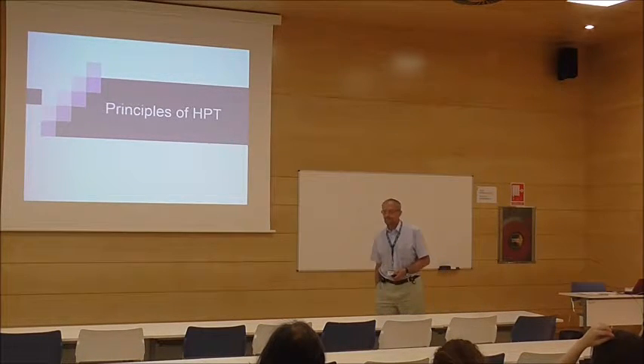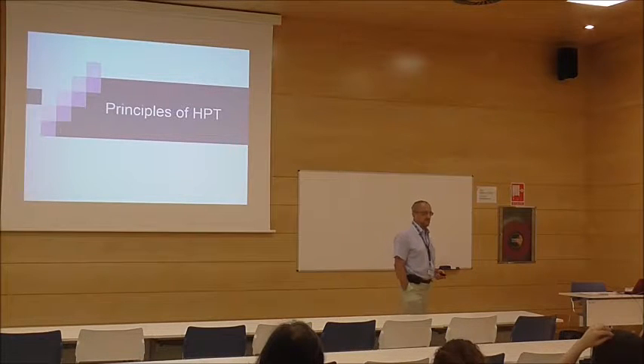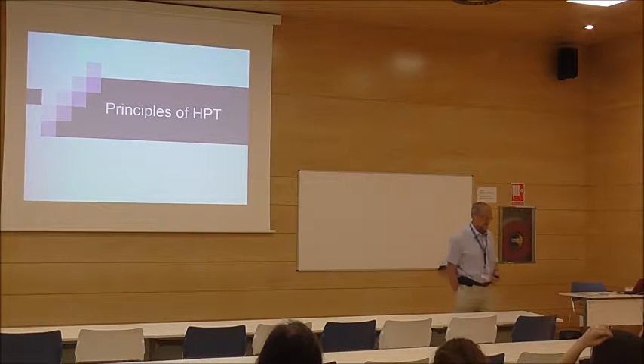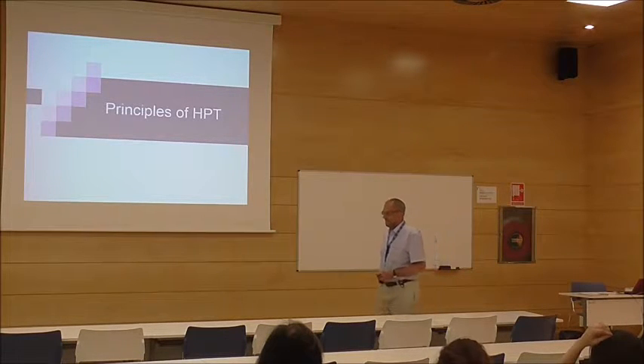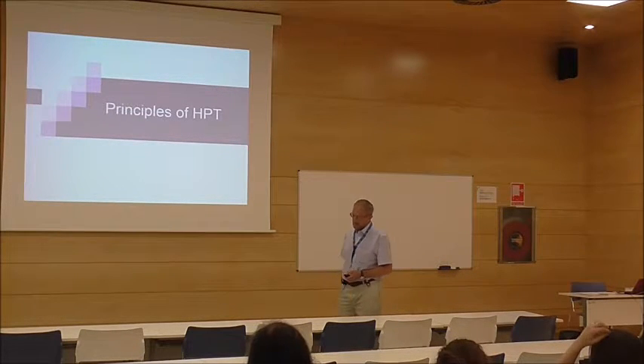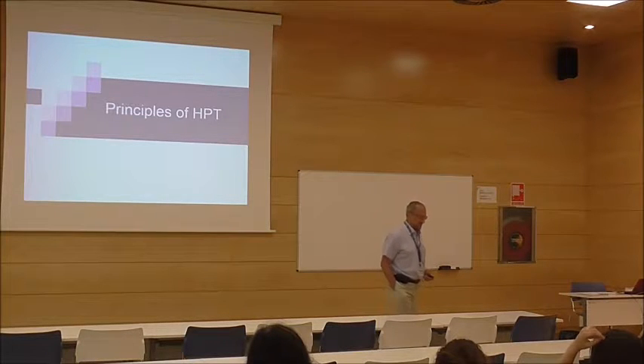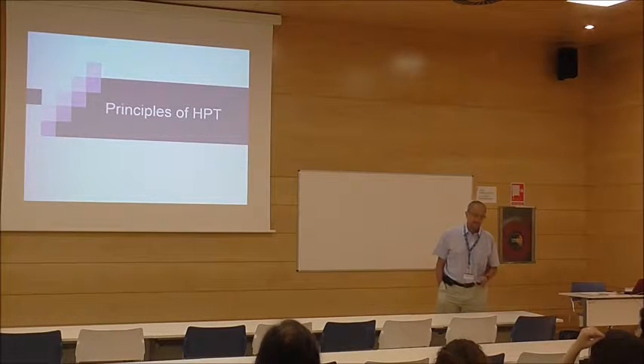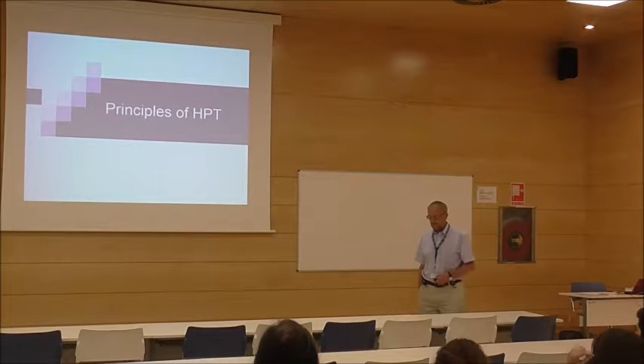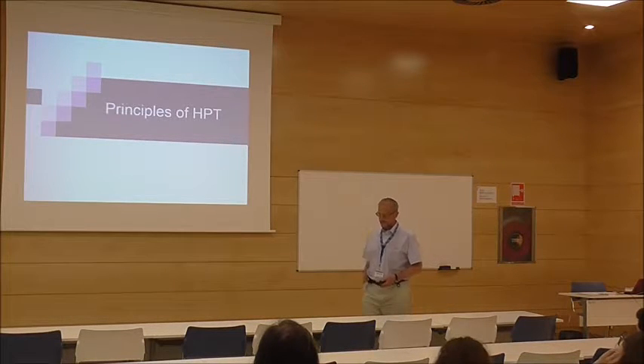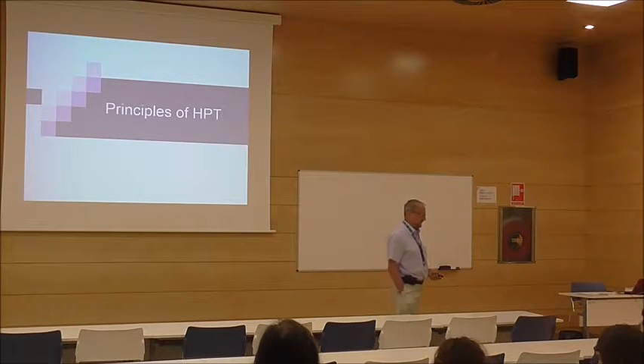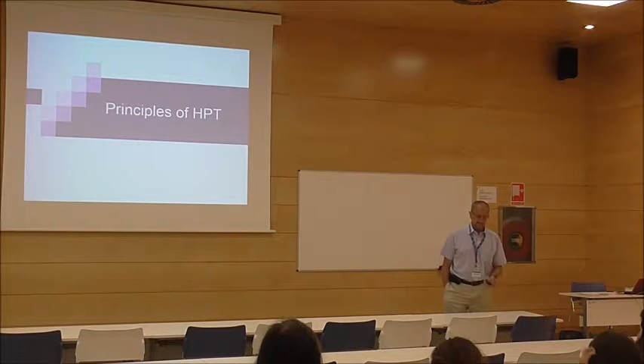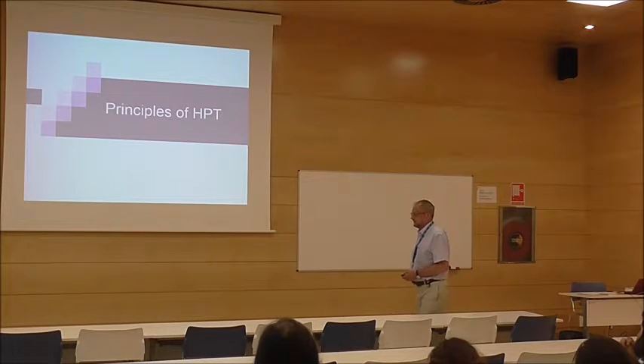Also, we have done some new work, not published, on ultrasonic treatment of nickel processed by ECAP and by HPT. Quite intriguing results, because depending on the amplitude, you can get further hardening of materials or softening. It's quite interesting, and also some work on